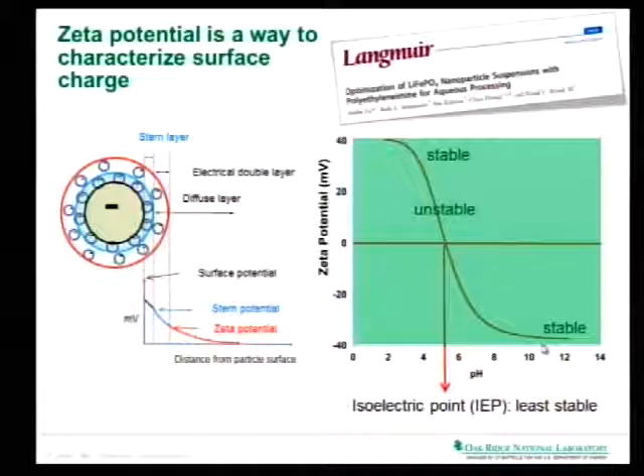What is very important to understand there is where your absolute neutral point is on a pH scale. That is very key because that allows you to select the right materials to disperse your particles. That's what we call a dispersant. If you go back about 5 years and look into the literature, people ignored that point, and they tended to use the wrong dispersants in the processing, and they had a hell of a time getting a stable dispersion.